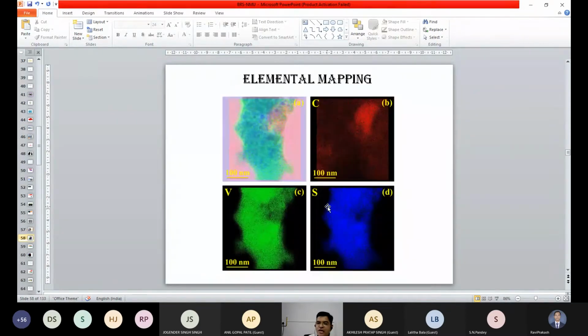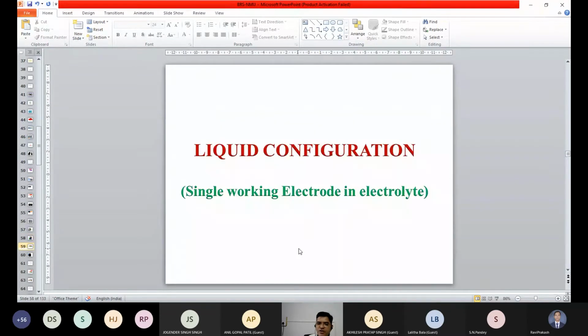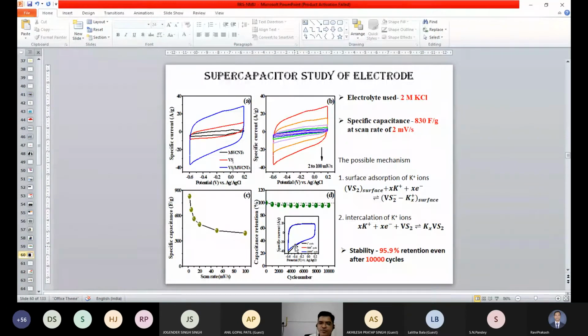So we have done elemental analysis to see whether vanadium is there, sulfur is there, carbon is there, so that you can confirm how uniformly or homogeneously it is coated, more specifically for this vanadium sulfide. Then we applied this for the liquid configuration, meaning we used a single electrode deep inside the electrolyte, another electrode of platinum, and also a reference electrode. We then did some studies in the liquid configuration to optimize the performance.